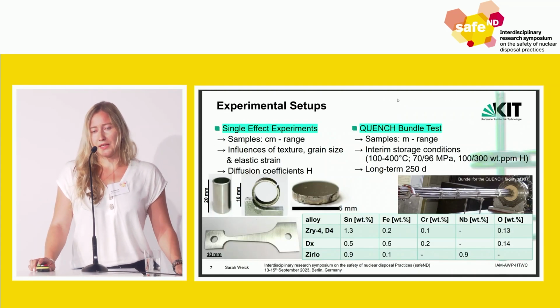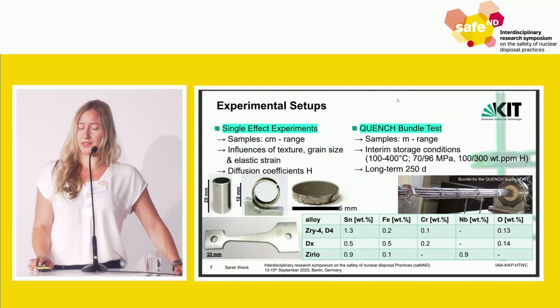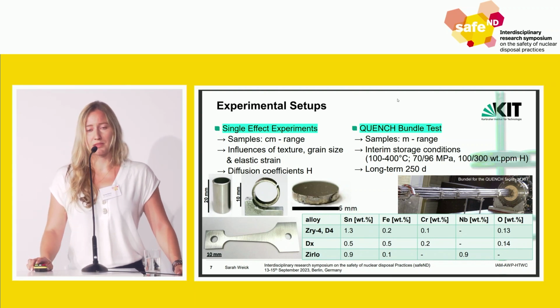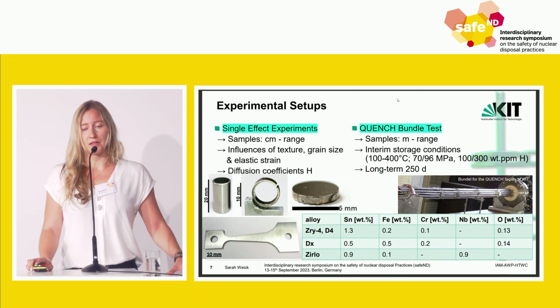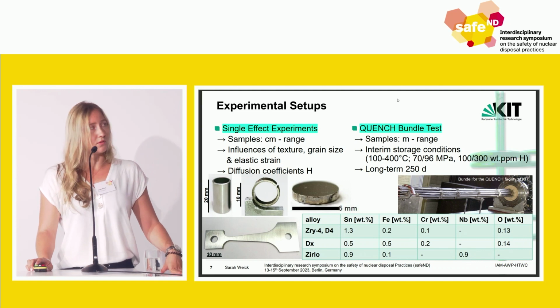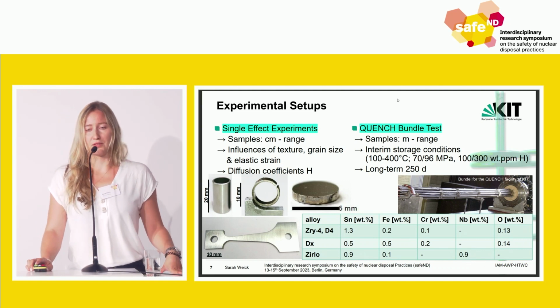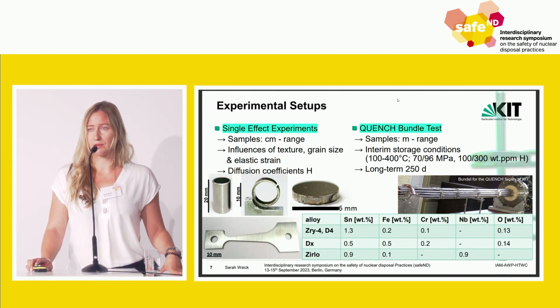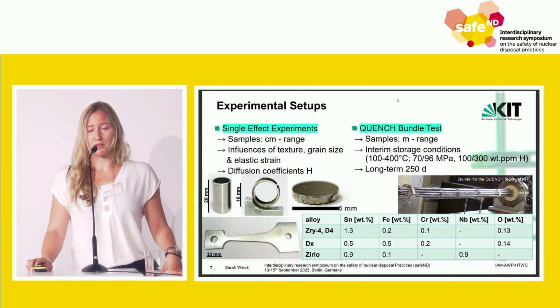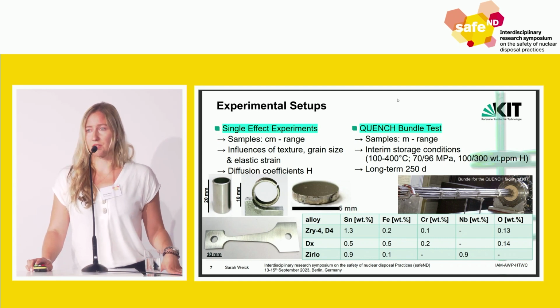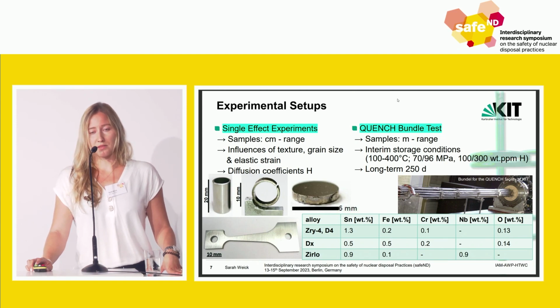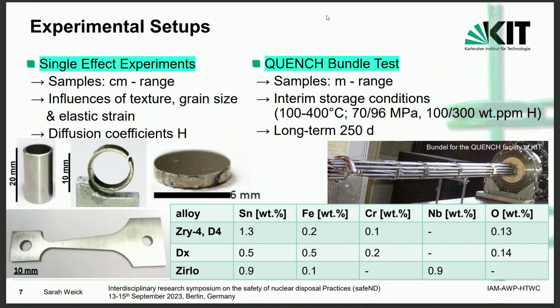To give you an idea about the experiments and setup made at KIT, related to investigating these effects and what happens with the hydrogen due to temperature and pressure conditions in the dry storage phase, we perform single effect experiments and also have a quench bundle test.